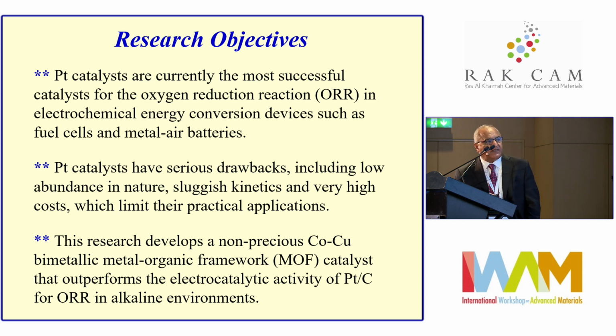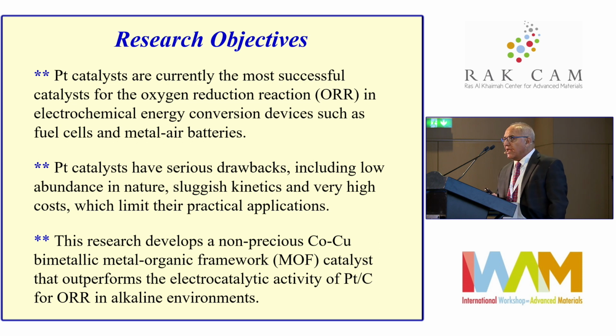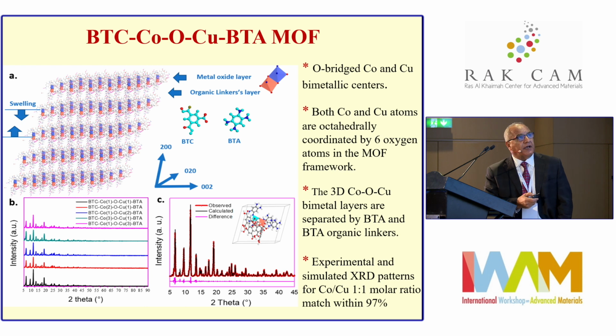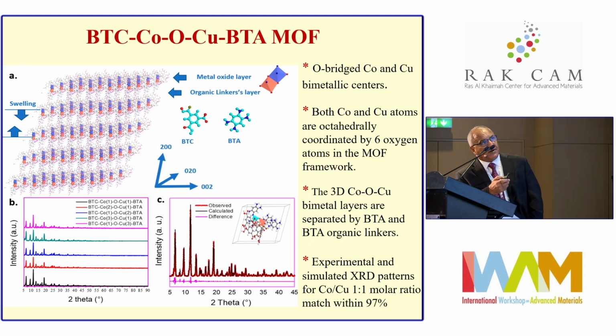So the goal here is to find a replacement that does not use any precious metals, and the idea came to construct the cobalt-copper bimetallic framework and use it as a catalyst to see if it can compete with the platinum catalyst in this case. So the structure here is made with copper and cobalt bridged by oxygen. So it's a metal oxide layer formed of copper, oxygen, and cobalt. And then we have two types of organic linkers, the BTC, which is benzene tricarboxylic acid, and BTA, which is benzene tetramine.